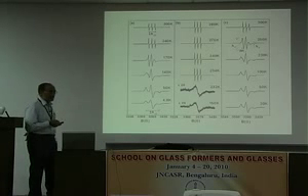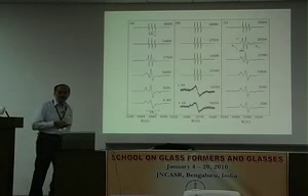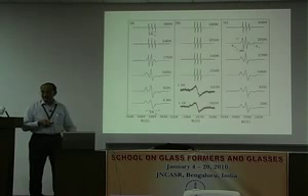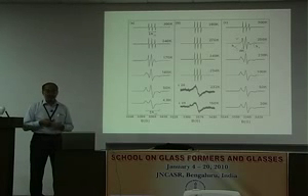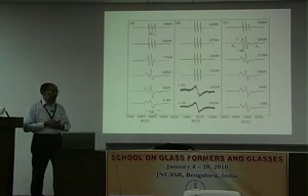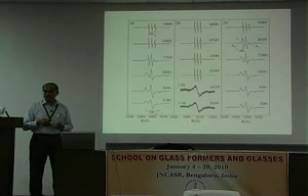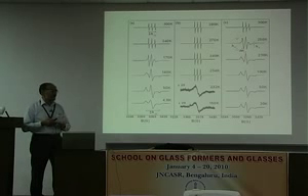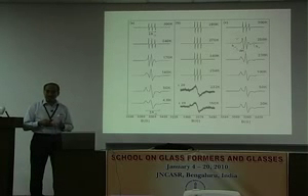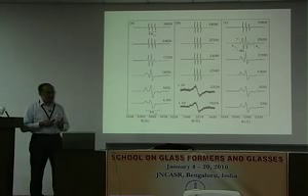For water, of course, most of you know there has been a controversy about whether it undergoes a glass transition at all. If so, what is the glass transition temperature? Is it around 135 Kelvin as quoted by some people, or like Professor Angell says, no, you cannot see a glass transition in water. It is preempted because of the crystallization transition. If at all a glass transition were to be there, it has to be 165 K.